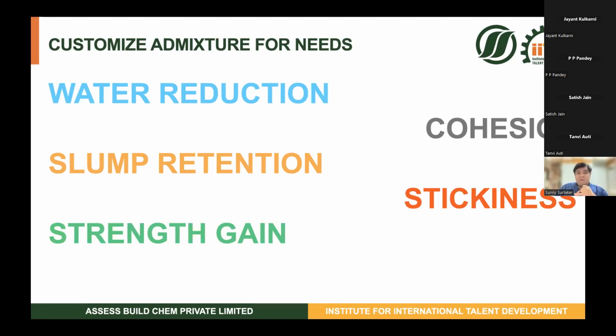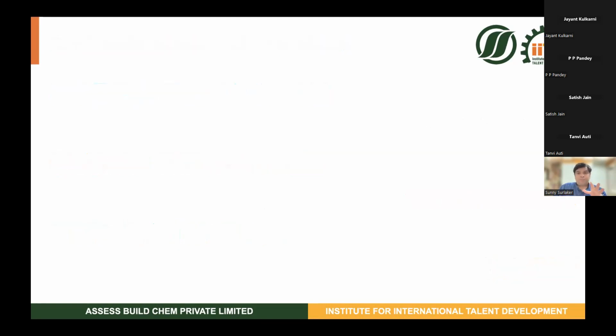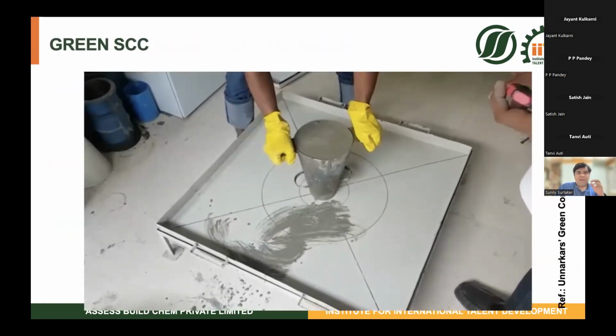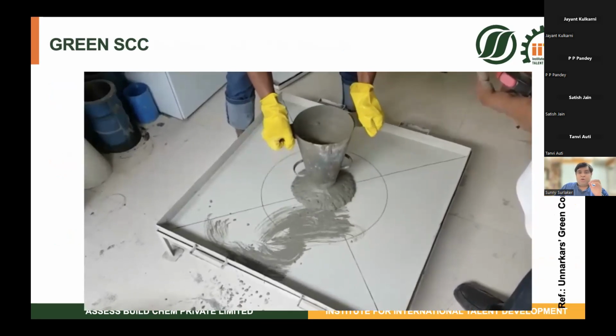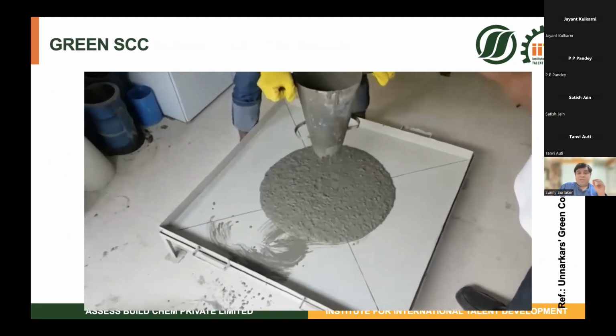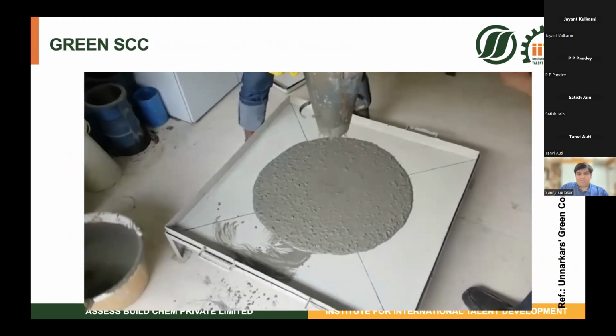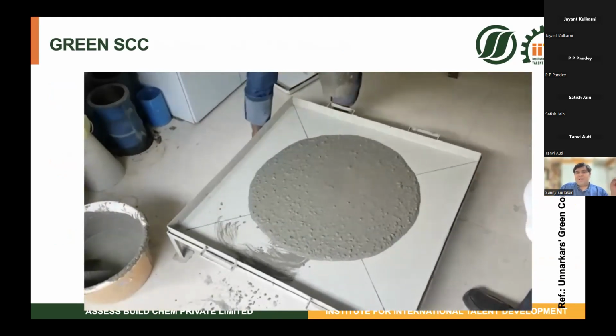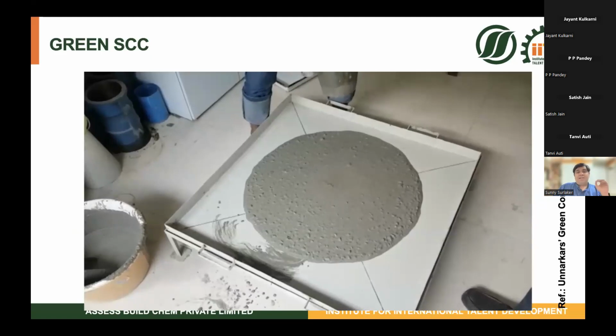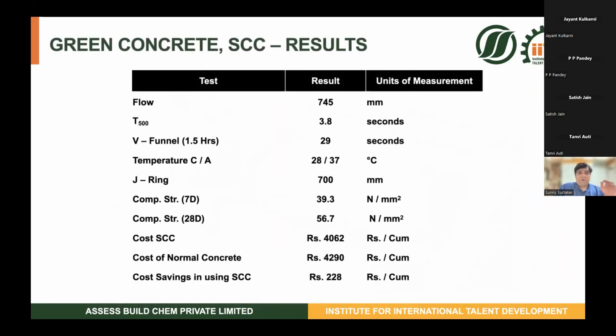Then, of course, because of the very high replacement of cement with GGBFS, this particular system still had to gain strength relatively rapidly so that the formwork could be removed. And last but not least, we had to take a look at the overall flow. It took us a few tries, but finally the results came through very nicely. This is 100% sand that we get from the local sources, made with aggregates up to 10 mm, and we could finally make a very nice SCC in the lab. This whole thing worked out pretty well overall in terms of the result.